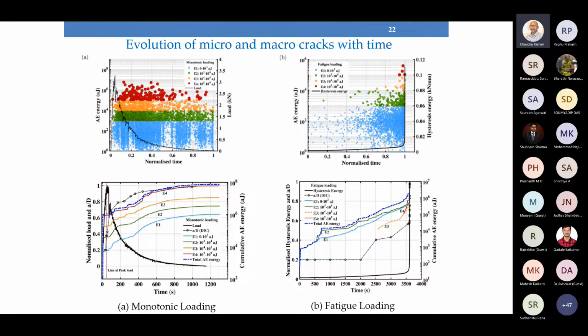So here, what we are plotting is the AE energy in attojoules. Okay, this is a normalized time. It can be normalized CMOD as well, because it was done under CMOD control with a constant rate. And this is the load on this axis. So the black line indicates the load versus time relationship, or load versus CMOD relationship. And these blue dots are the low energy events, meaning energy level from say 0 to 10 to the power of 3, 1000 attojoules. So these are the low energy events, followed by the green, the orange, and the red. So red ones are the high energy events.